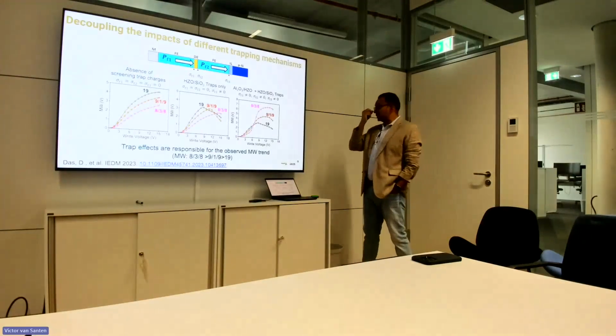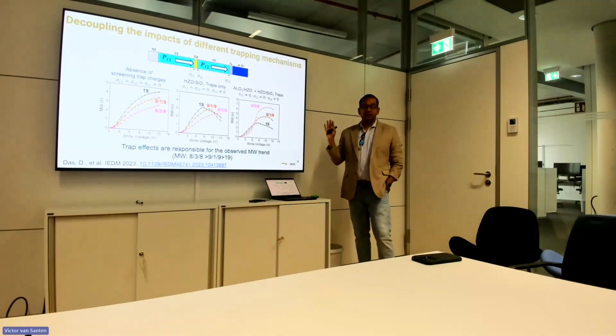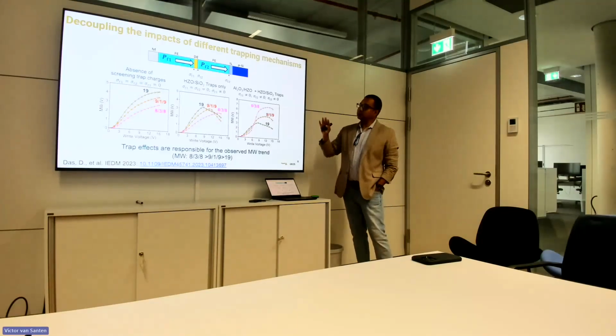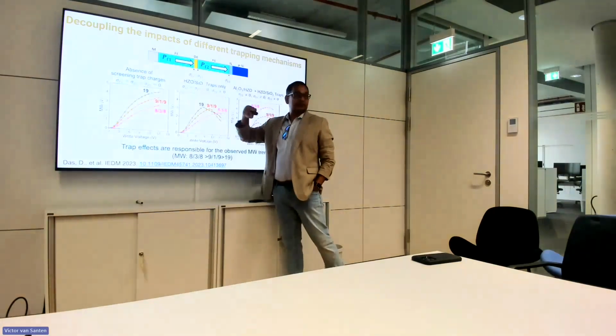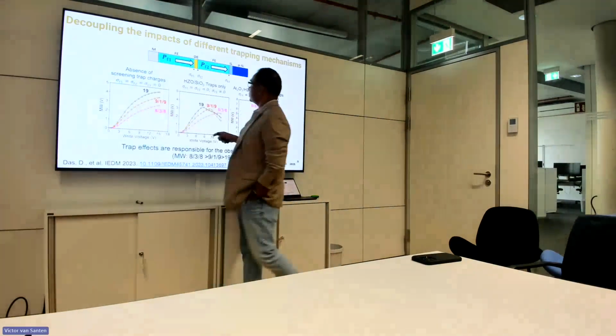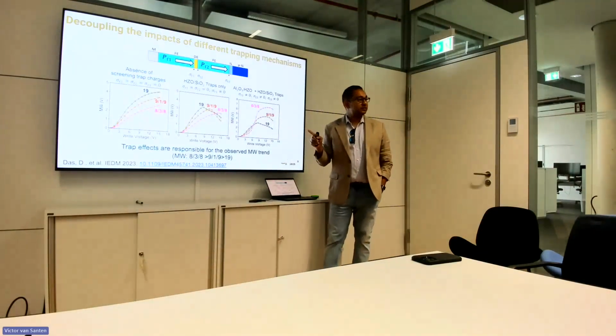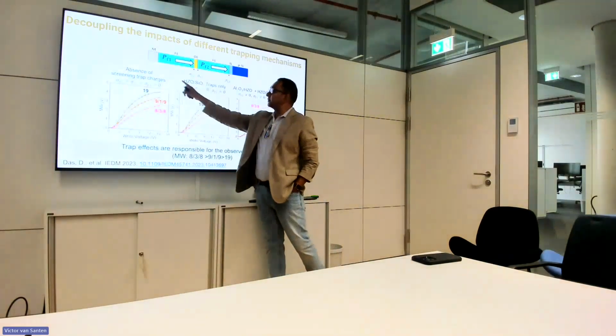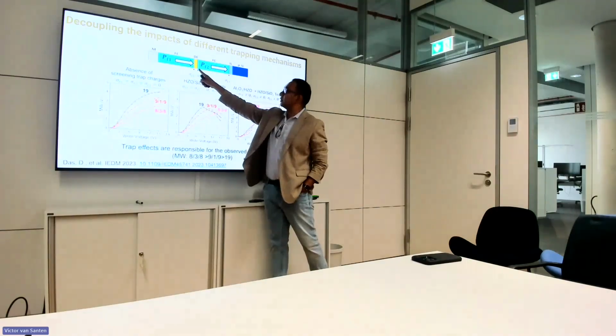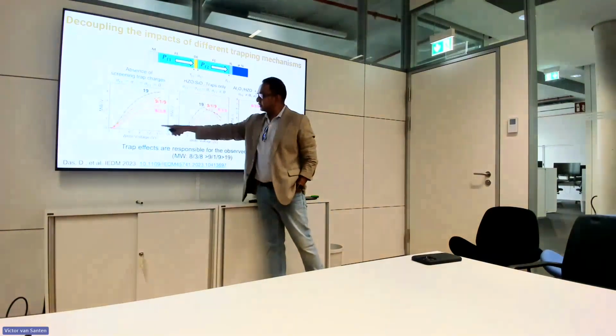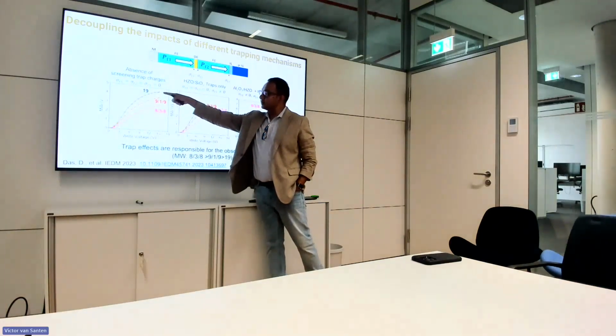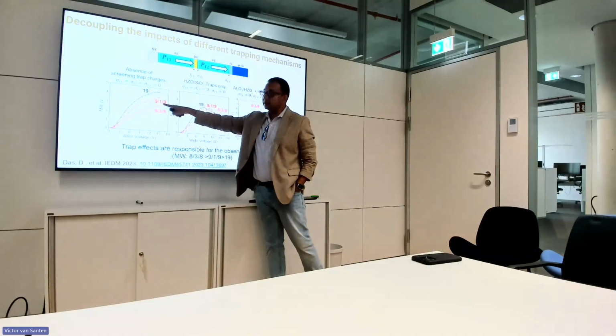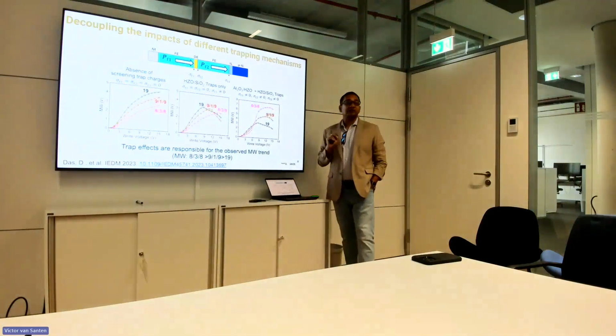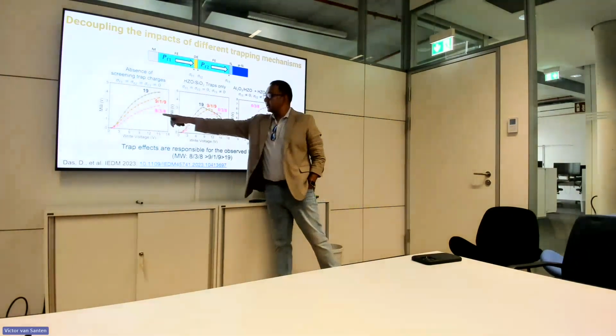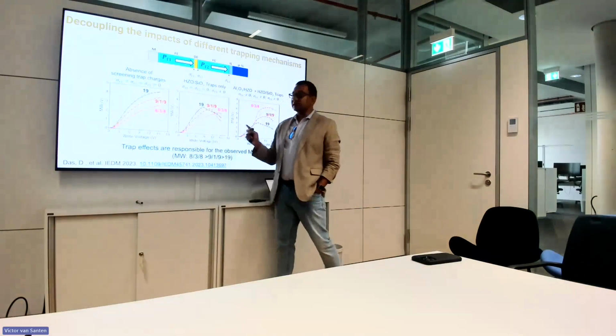So we did a simple coupled Schrodinger-Poisson simulation, coupled with a Preisach model of the ferroelectric, a simple model, where we also introduced the interface traps. Okay. So what I'd like to first show is three plots with different assumptions of traps. First, if we don't have traps at any of these interfaces, then you will see this kind of trend, where the write voltage memory window is largest for the pure HZO, then 1 nanometer alumina and 3 nanometer alumina. So it does not match what we are seeing in the experiment, because in the experiment 3 nanometer alumina has the largest memory window.